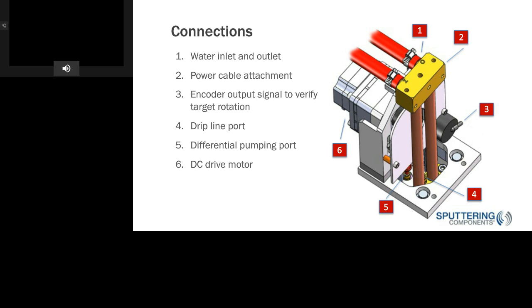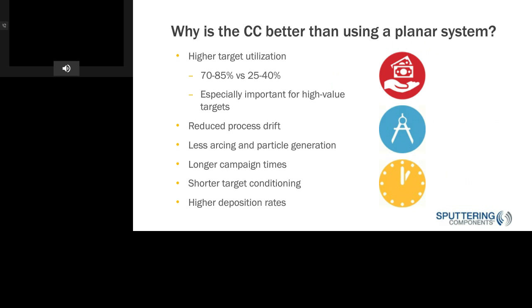So why is a CC better than using a planar system? Points that I've put down here really are common to all rotary cathodes when you're comparing to a planar cathode, mainly the higher target utilization, 70 to 85% you'll get versus 25 to 40% for a planar, which will be especially important if you're looking at high value targets, precious materials, or some ceramic targets.